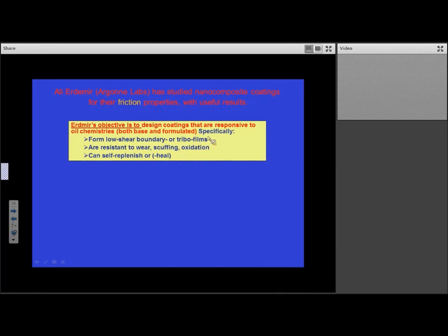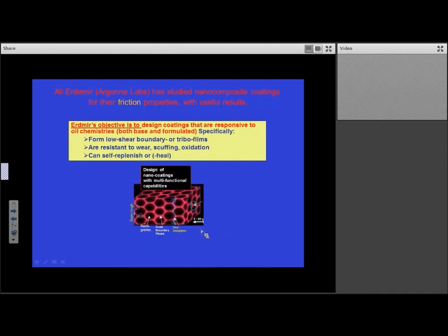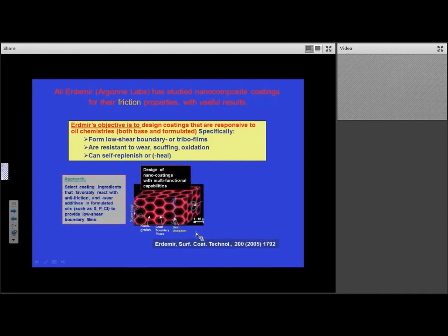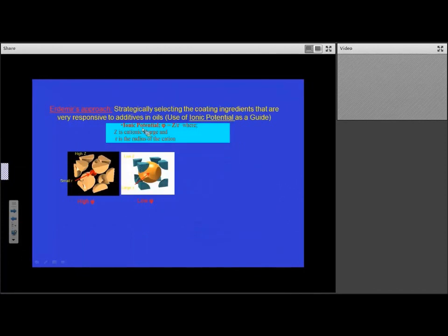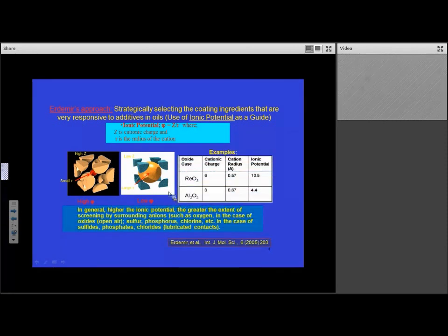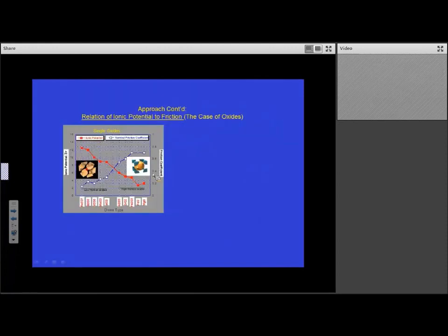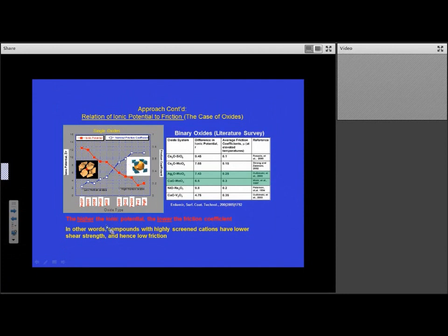I just wanted to mention quickly Ali Erdemir's work, which is not really related to our work on wear, but he looks at these materials from the tribological effect. And again, he looks at the nanocomposite from a toughness point of view, but also from the interaction effect in lubricated contacts. He looks at something that he calls the ionic potential, which is the cationic charge divided by the radius of the cation, and he talks about how this parameter, ionic potential, can enhance the performance in a lubricant. And he says that the higher the ionic potential, the lower the friction coefficient.